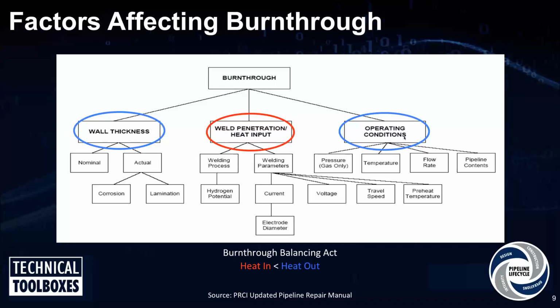So if you ask the welder to weld a little hotter, what welders typically do is they'll turn up the current. So they think their welding arc is hotter, which it is in reality. But what the welder also does, he tends to weld at a faster travel speed. So the welding heat input he's putting into that weld is actually lower, even though he's welding at a higher current.